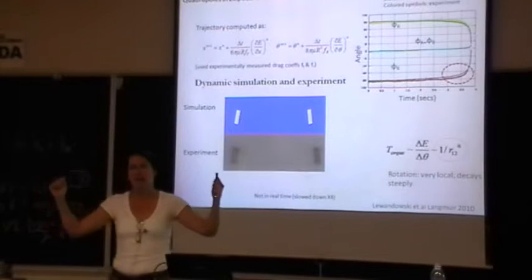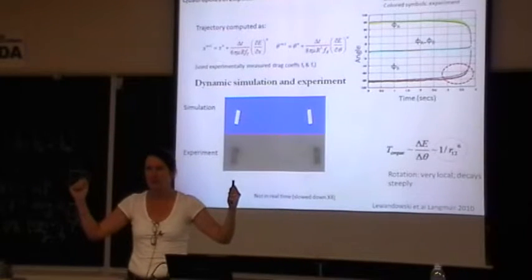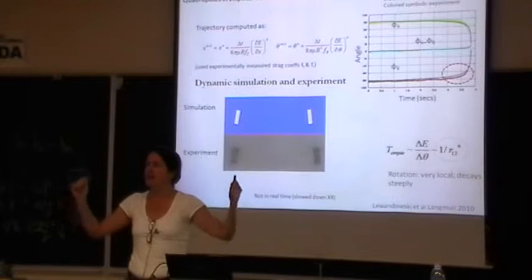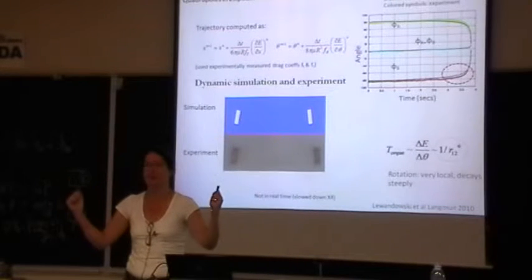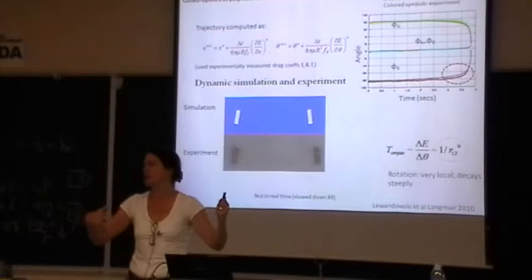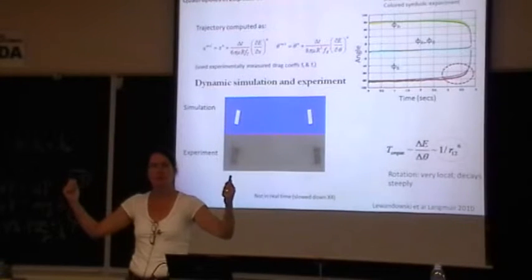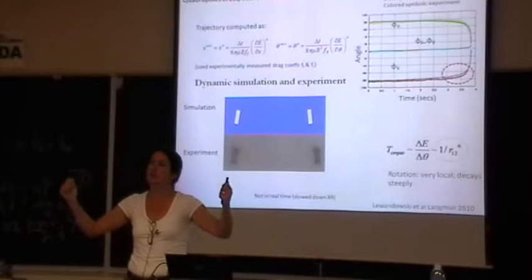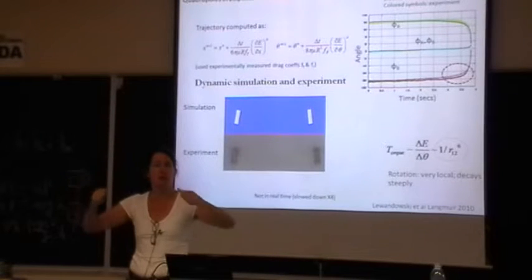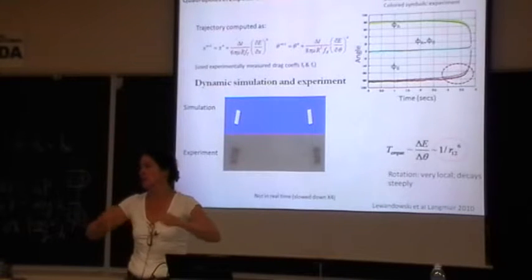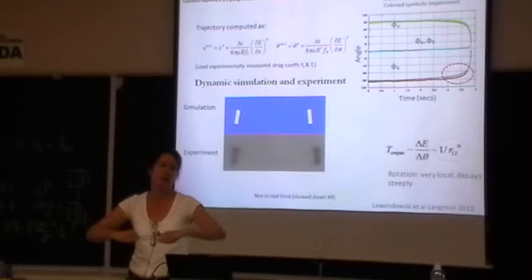We calculated the excess area associated with the interface. So we have an energy field, and the energy depends upon orientation and distance. There's a closed form expression which I'm going to spare you. But here we take that expression and use it in an explicit Euler scheme to update the position of the particle. What we need to add to that is a drag coefficient. We need one for translation and one for rotation, and we pull them out of experiment.